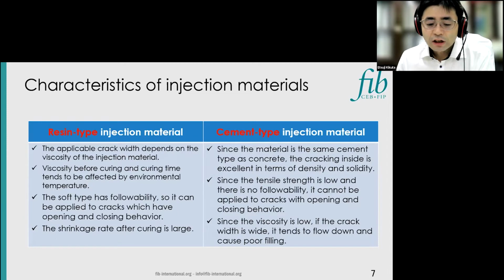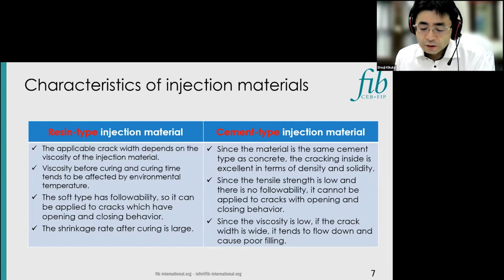About crack injection materials. Crack injection materials are broadly classified into resin type and cement type. In the resin type, there are products with various viscosities, and the applicable crack width depends on the viscosity. And since the viscosity of injection materials tends to be affected by temperature, ambient temperatures and concrete temperatures are important management items. Curing time is also affected by temperature.